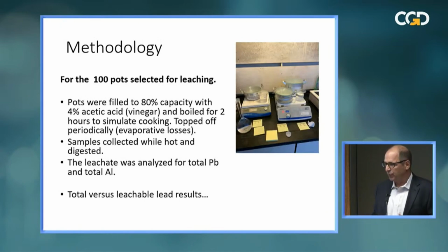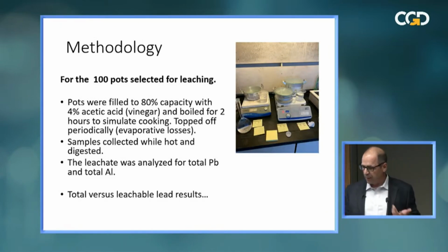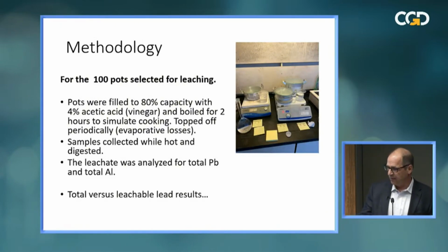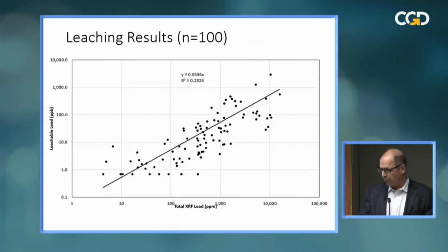So what we settled on was basically taking our 100 pots, filling them 80% with 4% acetic acid, boiling them for 2 hours, and testing the leachate for total lead and aluminum. Okay, and what do we find?